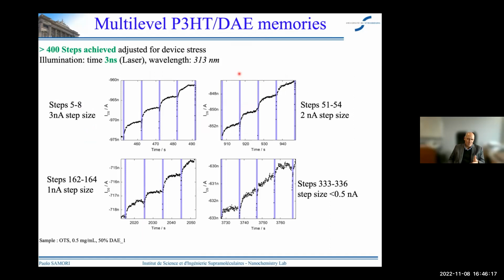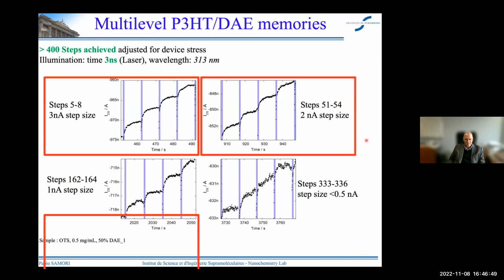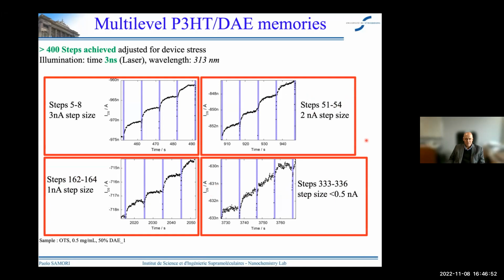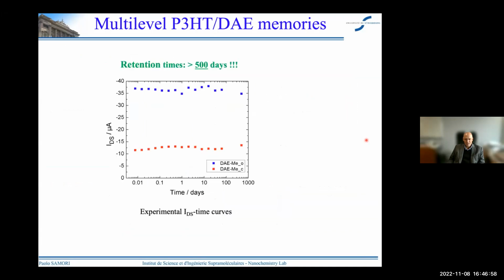And then if you want to see more closely, you can see that at the beginning of this kind of study, from step 5 to step 8, you have a 3 nanoamp step size difference between adjacent steps. By increasing the number of steps from 51 to 54, we have 2 nanoamps. From 162 to 164, we have 1 nanoamp. And from step 333 to 336, you have less than 0.5 nanoamp. So these are well-defined, highly reproducible, and therefore it allows us to access over 8-bit storage capacity.